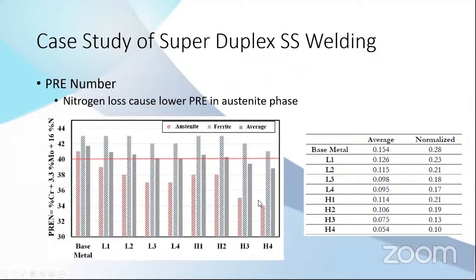And this is what happened in the weldment area. This is what I've said before: low heat input 1 pass, low heat input 2 pass, high heat input 1 pass, high heat input 2 pass. There is a very low austenite phase balance in the weld area. The higher the heat input, the less austenite balance. Why? Because nitrogen is being lost. You're losing nitrogen if you are using only argon gas. The nitrogen gets out to the atmosphere. That's why the austenite phase is very low. The ferrite content is not affected by nitrogen, so it still remains very high.